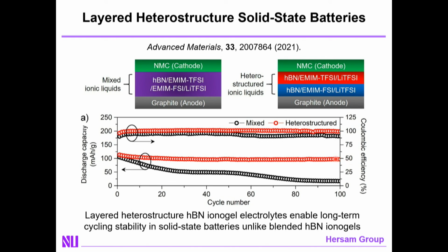I would say probably almost ready to go commercial, but there's one final problem, and that is the way in which we made these ionogels initially was to take hexagonal boron nitride and ionic liquid, put it into a mortar and pestle and just grind it, and then slap it onto the electrode, compress it in a coin cell, which is good enough to publish a paper maybe, but I would say not a scalable manufacturing strategy.